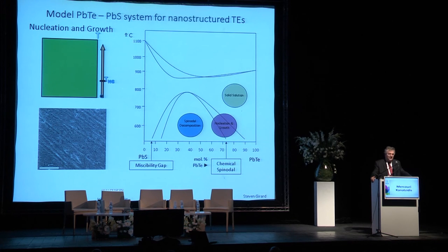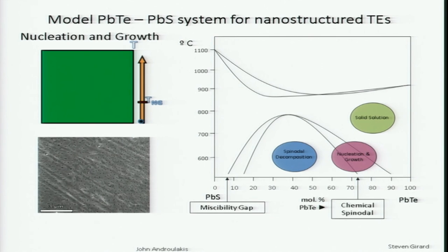So we proved that these nanostructures are, in fact, responsible for this by making a material that first didn't have any nanostructures, but it was metastable, and then we heated it up to develop stable nanostructures, and we were monitoring the thermal conductivity from the state that it didn't have nanostructures to the state that it did, and we saw that the thermal conductivity was lower.